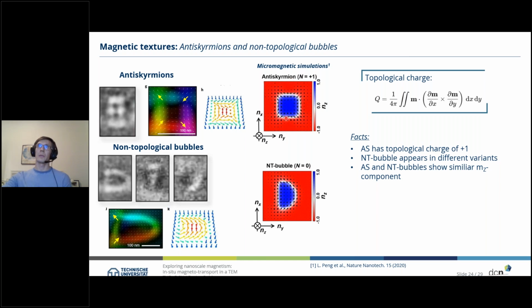But what we also see from that micromagnetic simulation is that the Z component of the magnetization for both systems is nearly the same. And that is interesting because that is what we are sensitive to with the anomalous Hall effect, since there we are sensitive to the out-of-plane magnetization of our sample. Whereas with the Lorentz TEM, we are sensitive to the in-plane magnetic induction of our sample, where we can see differences between these two magnetic features.